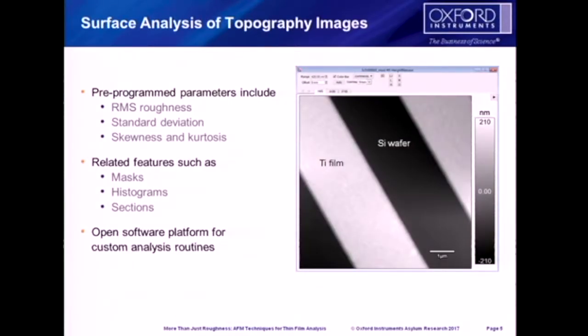Now let's talk more about how you can use the AFM. So here's an example of titanium film deposited on a silicon wafer. Now traditionally, AFM topography measurements have been processed to give you roughness measurements. And most common numbers people think about are RA and RQ. Now RA and RQ can give you some information, but there is many more things you can learn about the sample. So you would like to know what is the skew and what is the kurtosis, or you want to find all the different S parameters that are available that give you information beyond the simple RA and RQ of the film. So how would you go about making this analysis? So let me walk you through a few steps.